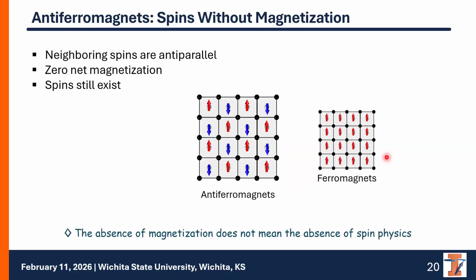So in this work, I investigated antiferromagnetic materials. In antiferromagnetic materials, the neighboring spins align in opposite directions. So generally, the antiferromagnets have zero net magnetization, nearly zero net magnetization, because they are all compensated. The zero net magnetization sounds like a big problem in spintronics because most of the spintronic phenomena rely on the magnetization. However, the important thing is that spins still exist in this material. Even though they have zero net magnetization, the microscopic spins are still present and ordered and dynamic. So the absence of magnetization does not mean the absence of the spin physics.